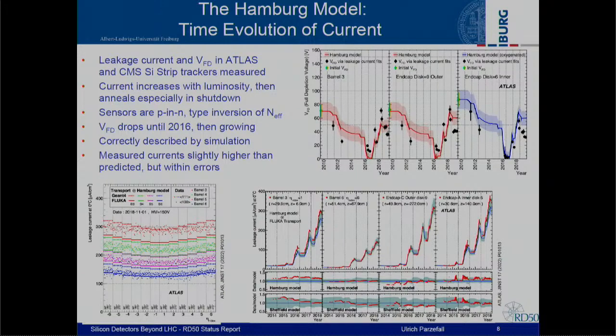This is more detail than I can go through at this time, but I'll point out that, by and large, we have good agreement between what the Hamburg model predicts in terms of leakage current, shown here for different parts of Atlas barrels and end cap disks. You can also see a continuous increase as we keep irradiating, and sometimes a drop when, during shutdown, we warm up the detector for a little bit.